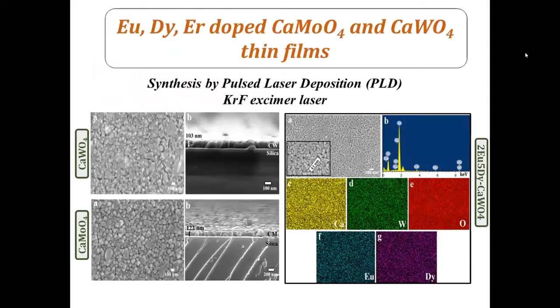We have also prepared their thin films because for device miniaturization, we would like to have their thin films. So we prepare thin films of calcium molybdate and calcium tungstate by pulsed laser deposition. And the cross-sectional STEM studies show that the thickness of the film is around 103 nanometer, about 100 nanometers. And there is a fairly uniform distribution of calcium, tungsten, europium, and dysprosium ions in the film.